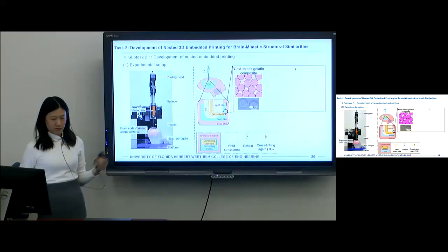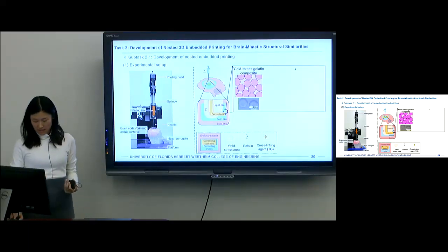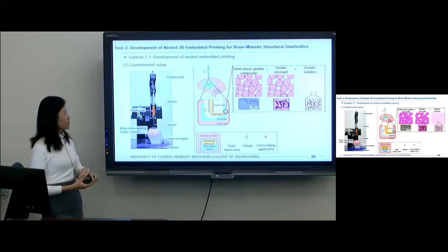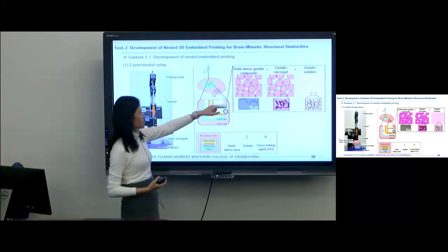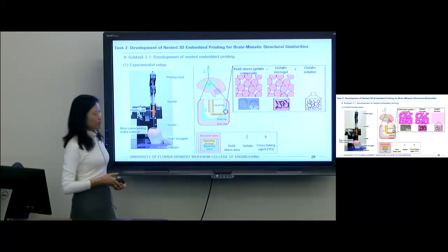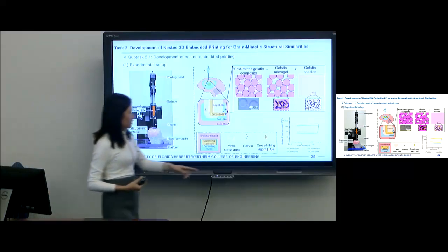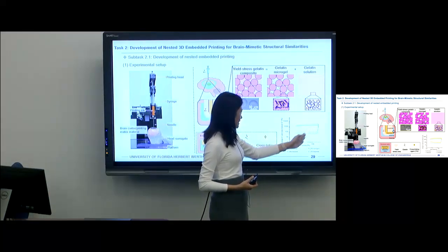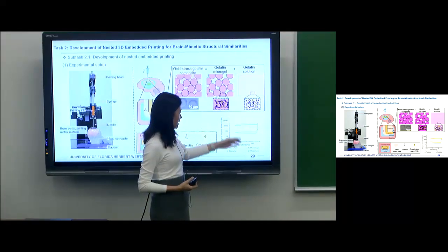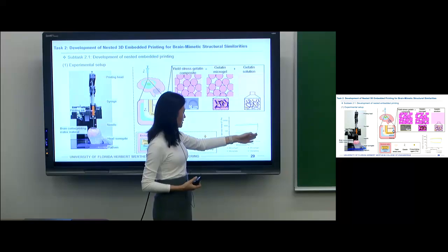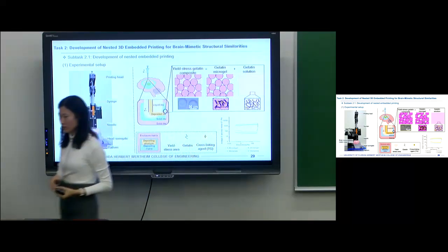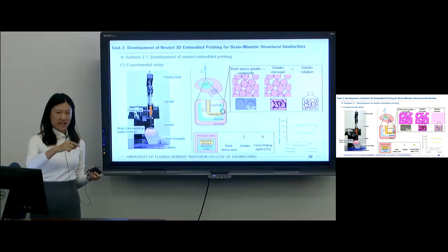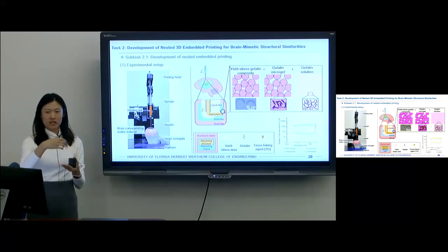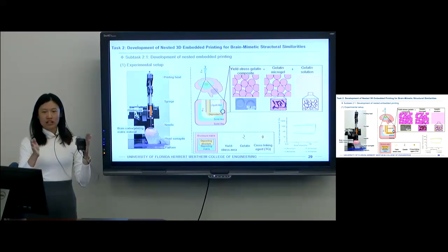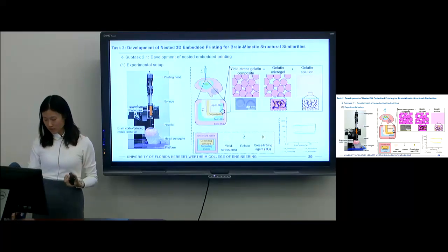So this is our setup for the brain simulant printing. As we mentioned previously, we will use gelatin composites, which consist of gelatin microgel and gelatin solution, and this will behave like a yield stress material. When the shear stress applied is less than the yielding point, it will behave like a solid-like material. When the shear stress is larger than the yielding point, it will behave like a liquid material. This allows us to deposit the material on site, and after the nozzle travels away from the region, the shear force disappears, and it will trap the deposited filaments inside of it, because it will recover to a solid-like material.